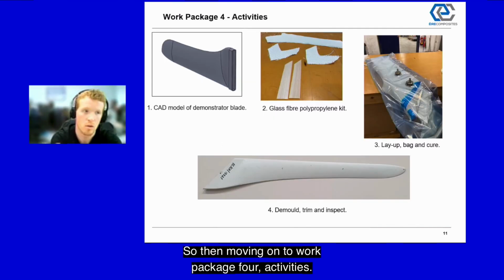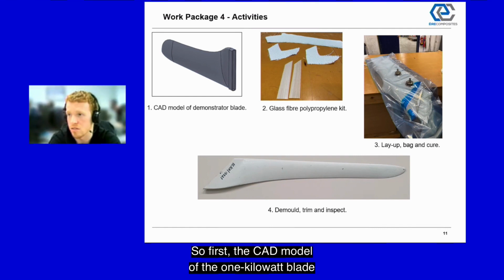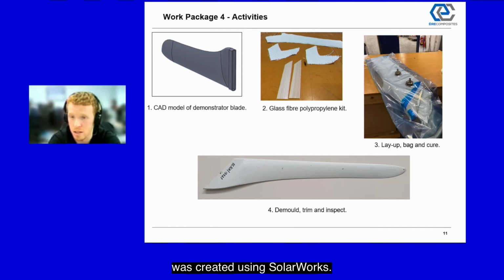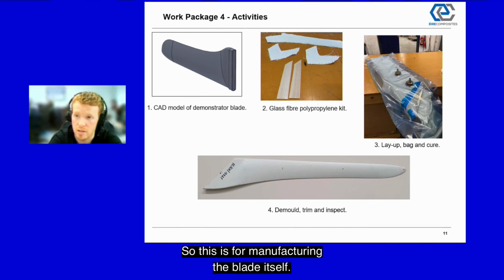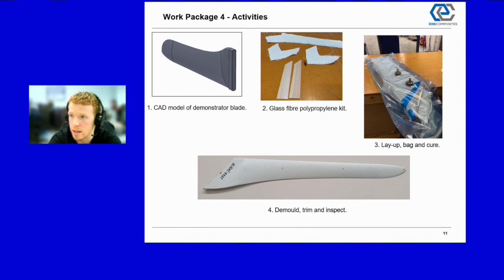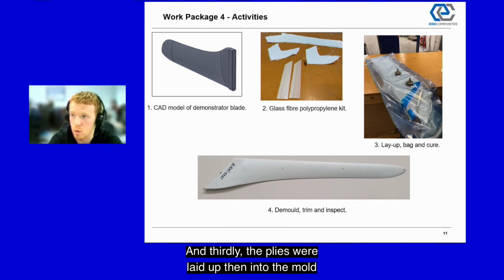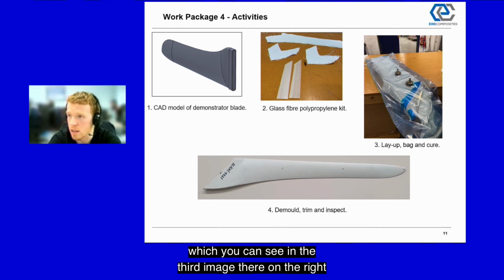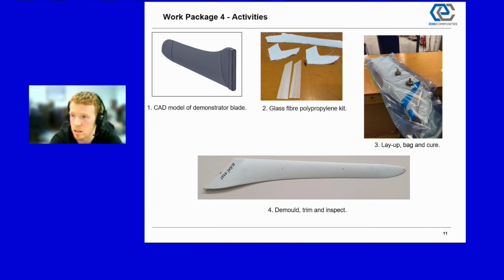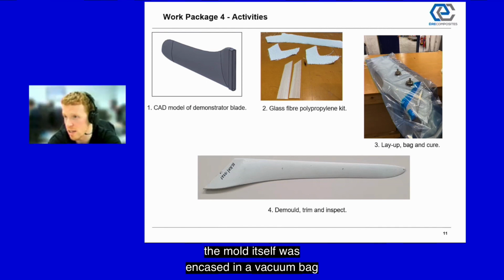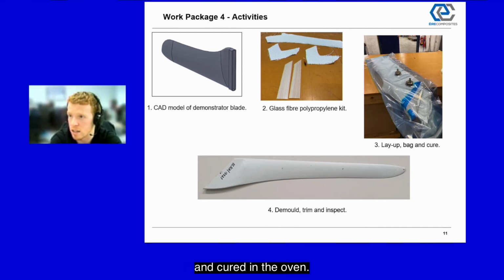So then moving on to work package 4 activities. First, the CAD model of the 1 kilowatt blade was created using SolidWorks. Secondly, the glass fiber polypropylene plies for the blade were kitted. So this is for manufacturing the blade itself. And thirdly, the plies were laid up into the mold, which you can see in the third image there on the right. And the mold itself was encased in a vacuum bag and cured in